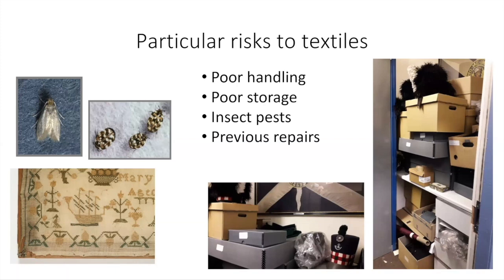I think that another factor that can also be a particular problem for textile conservators is previous repairs. Most people who can sew think that they can repair textiles. So our historic textiles have often suffered many cycles of inappropriate repair, which can cause more harm than good in the long run. A patch applied over an area of damage can easily lead to further damage, as the stresses are pushed outwards into what were originally sound areas. So textile conservators take this into account when they're planning support treatments and think about the textile as a whole.